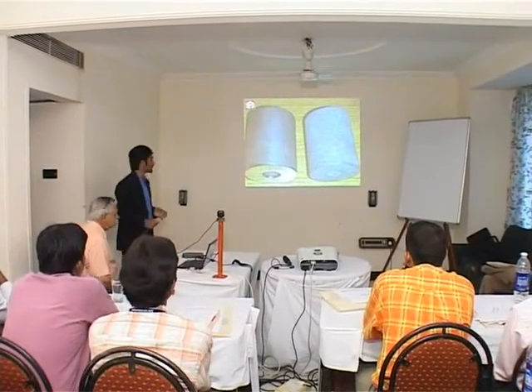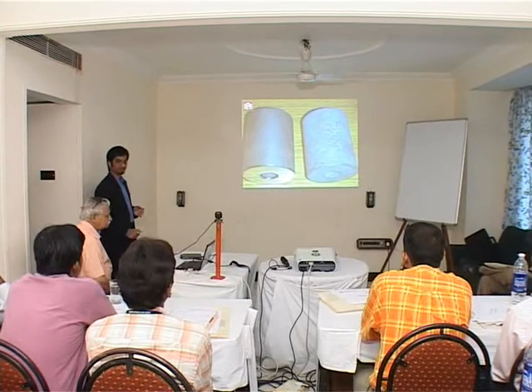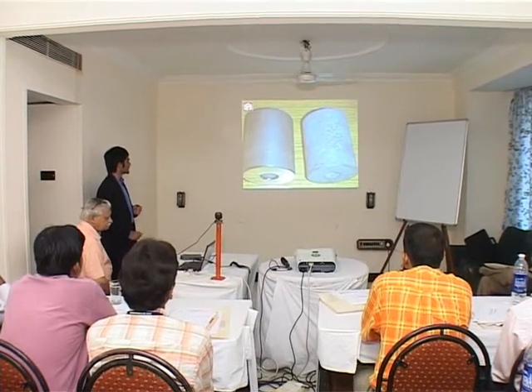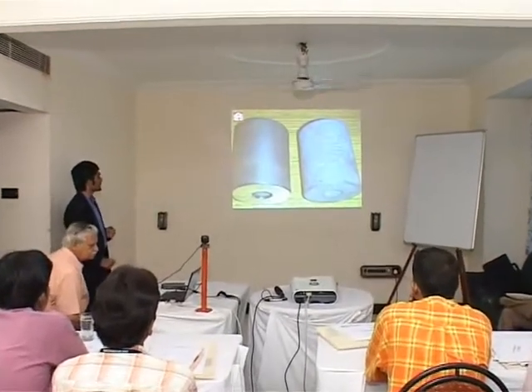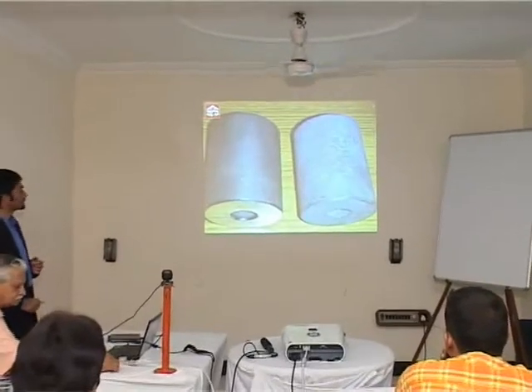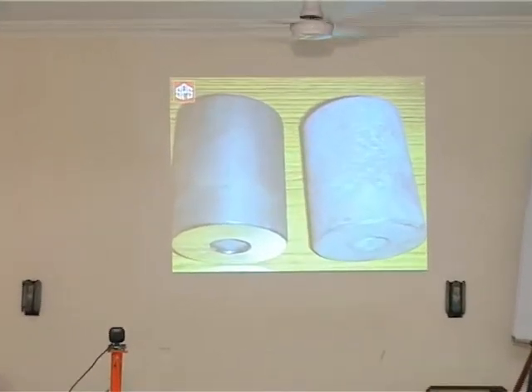This again is a component which was not coated against a component which was coated. This area again we have done very little bit of buffing, and you can see it's almost a mirror finish that we have achieved over here after buffing.